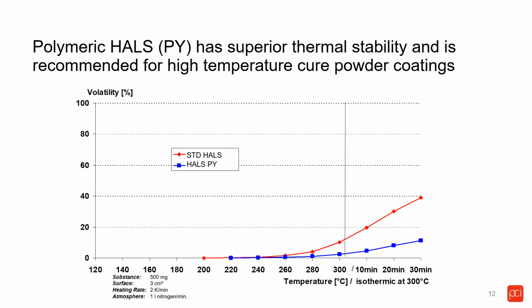Here again, the volatility, when we compare those HALS, percent volatility at different temperature and time, and we really see that the temperature and the isothermal reactions are favoring significantly, and that makes a lot of sense. Again, being polymeric, you have this high molecular weight. It cannot just come out of the coatings as easily as a standard molecule. So really superior thermal stability, and really highly recommended for high temperature cure powder coatings.